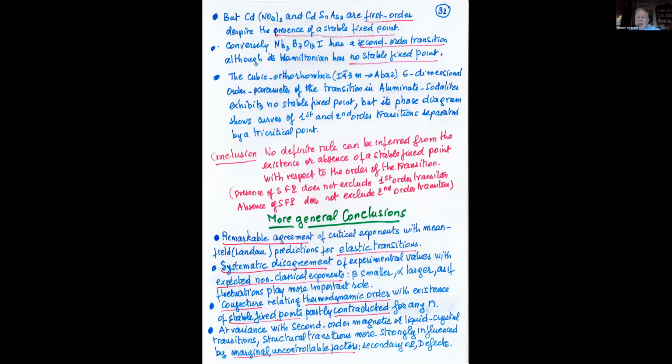Slava, I want to address your question about the ferroelectric uniaxial materials. When the ordering is ferroelectric and the interaction is dipole-dipole interaction, it changes the propagator at q equals 0 in Fourier space. That is why all those systems are shifted from the upper critical dimension of 4 down to the upper critical dimension of 3, and they have logarithmic corrections. However, if you have an anti-ferroelectric order parameter, then the action is not at q equals 0, the action is at q equals pi, pi, pi. At that point, the dipolar interaction behaves nicely, and therefore the propagator is practically the same as for short-range interactions. So the difference is between ferro and anti-ferro.